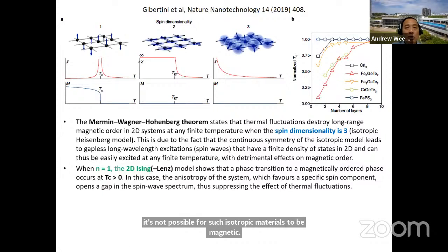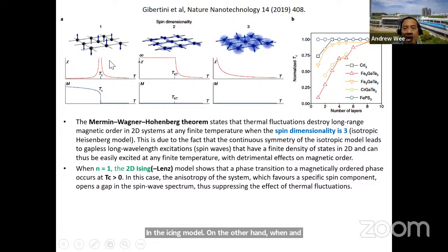In the Ising model, on the other hand, when N equals 1, you can get a phase transition to a magnetically ordered system since there is anisotropy in the system, right? It's up and down only. And it favors a specific spin configuration. And this opens a gap in the spin wave spectrum, which suppresses the effect of thermal fluctuations.